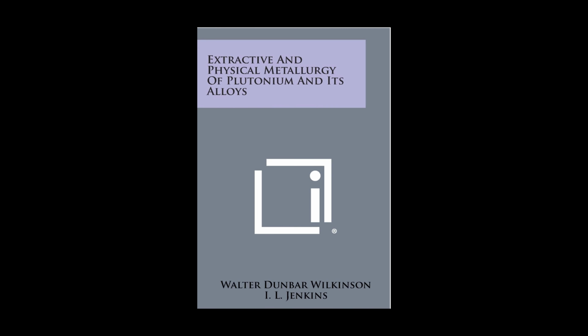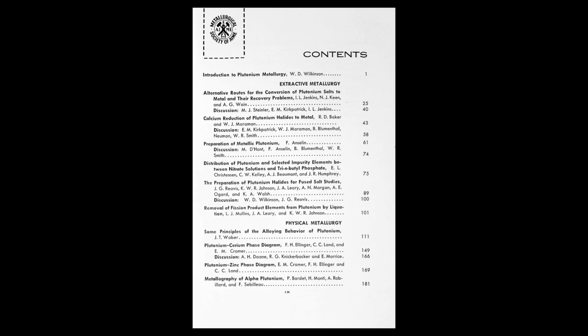Interesting trick. And they weren't just doing this with tiny amounts, right? You said Los Alamos scaled this up. Oh, absolutely. Their research showed this calcium reduction method worked well at scales from just a few grams right up to kilograms of plutonium per batch. Kilograms? Wow. And the purity? They reported typical yields with purity over 99% by weight. Table 3 in the source actually breaks down the best conditions they figured out for different scales using both the chloride and the fluoride starting materials.